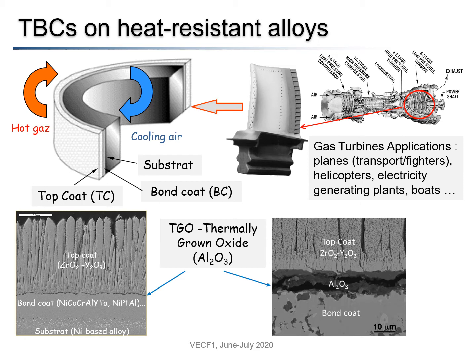This TGO layer often causes the poor mechanical behavior and degradation of the system. This layer also forms the two most important interfaces where fracture typically occurs. One interface is between top coat and TGO, and the second between bond coat and TGO.